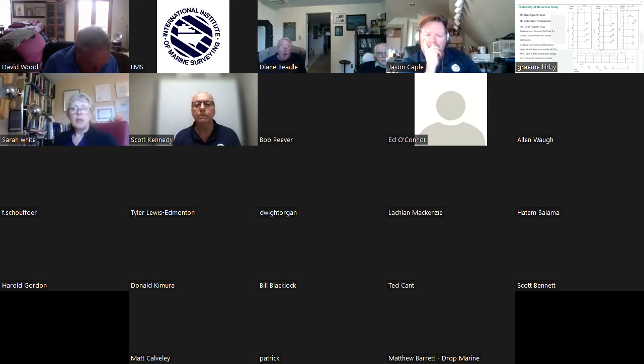So what we've done is we've done extensive field trials, we've done extensive probability detection studies, and we had specifically for LR class endorsement, we've had 4 specimens manufactured, which have a range of flat bottom holes to simulate localized corrosion. And then in the bottom of your screen on the right-hand side there, you can see it's a giant step wedge. So just like the small block I showed you before for the UTM calibration, this is a giant step wedge, and it has different levels of thickness incrementally, 20%, 40, 60, 80. And what we set out to achieve here and demonstrate is the accuracy and precision at each liftoff for every thickness that you'd encounter on a vessel.